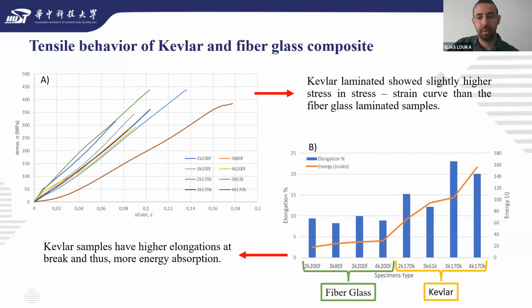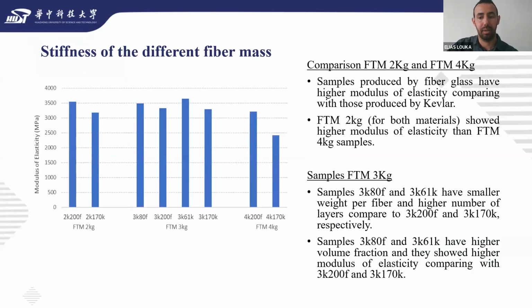The figure here shows the elastic modulus for all samples. In comparison, in cases of fiber total mass of 2 and 4 kilo, the samples produced by fiberglass had higher modulus of elasticity compared with those produced by Kevlar. This is because fiberglass samples have smaller total thickness and lower total weight compared to Kevlar samples. Fiber total mass of 2 kilo for both materials showed higher modulus of elasticity than the sample of 4 kilo.